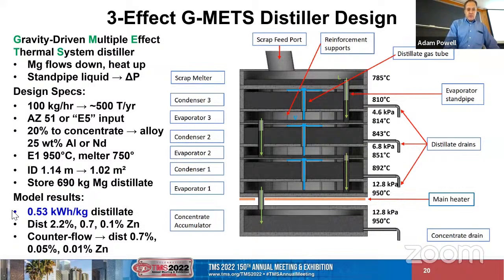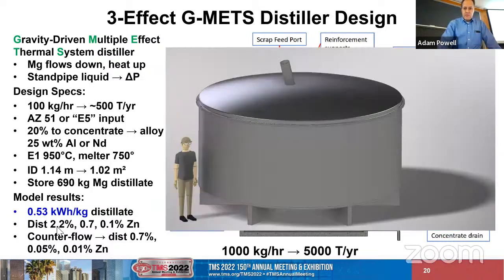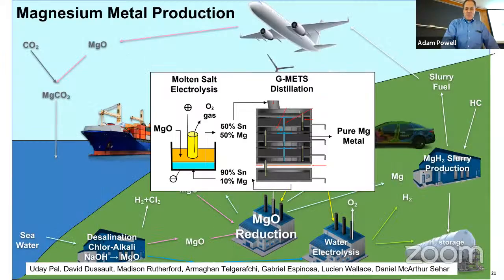So the model shows this uses about 1/3 of the enthalpy of vaporization as the input energy. In practice, small scale in the lab, we've been able to get 2 kWh per kilogram, which is just over the enthalpy, and about 60 to 80% less than the 5 to 7 kWh per kilogram used in industry today. So that's the basic how the technology works. You can scale it up just by making it wider, and so that's the process.